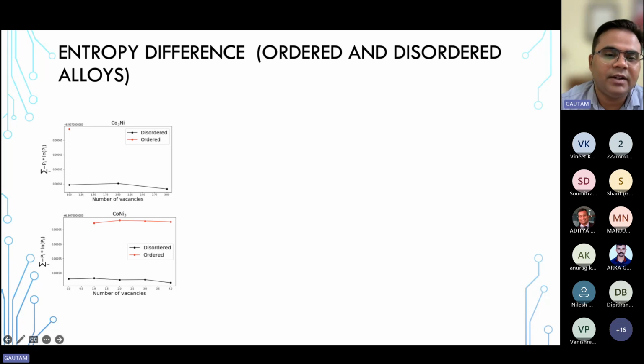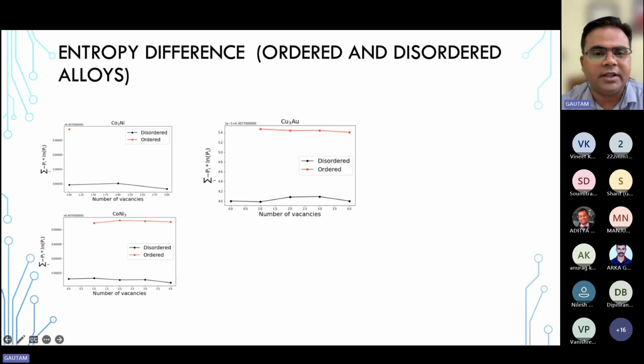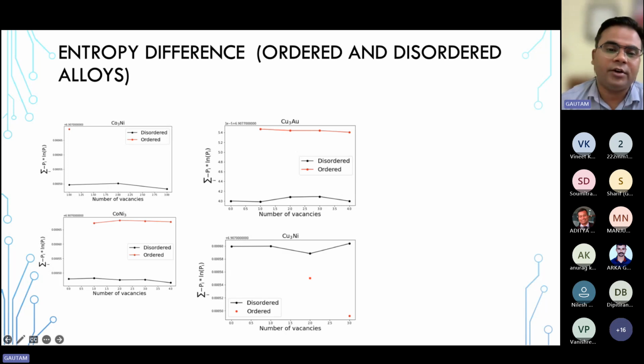Similar thing we were able to prove for cobalt nickel 3. In both of these cases, L12 kind of ordering is possible. With this information entropy approach, we were able to predict the order-disorder phase stability. Then we got excited and started to apply it to different cases. Say copper 3 gold, which is again a case. We are able to predict the ordered structure there also. And if we replace gold with nickel, this changes. Now the disordered phase is stable.